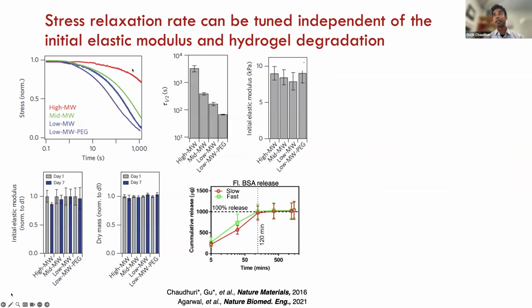So if we look at these stress relaxation curves on the top panel here, we see that as we go from high molecular weight alginate to low molecular weight alginate, we get faster stress relaxation. So we can quantify this by looking at the time it takes for the stress to relax to half its original value. And that varies from thousands of seconds down to about a minute. That overlaps with the physiological range that we saw earlier.